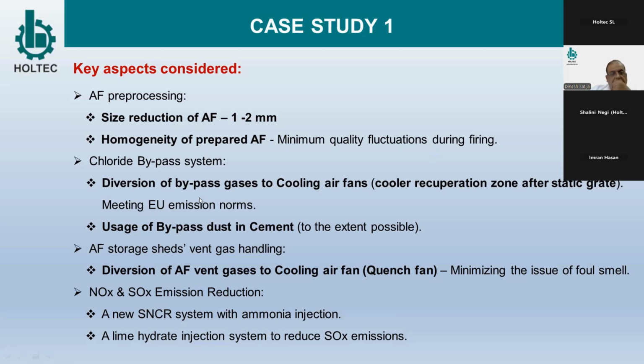Then, chloride bypass. The bypass was extended, but no separate vent was provided. All the bypass gases were fed into the cooler recuperation zone after static grate, so the cooler vent gases were going into the cooler. There is no separate vent because there are certain norms in the EU for that. That was a concept which was followed. And of course, the bypass dust was later added into cement.